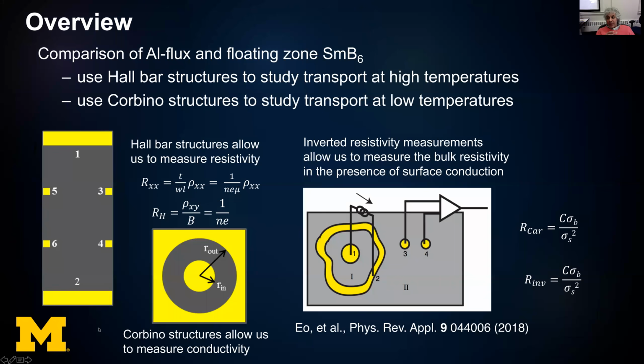We're going to be using different transport geometries. At high temperatures, we'll be relying on the well-known Hall bar structures. At low temperatures, we're going to use Corbino structures. There is a challenge at low temperatures because the material has surface conduction. So in order to extract information about bulk conductivity, we will be using inverted resistance measurements.